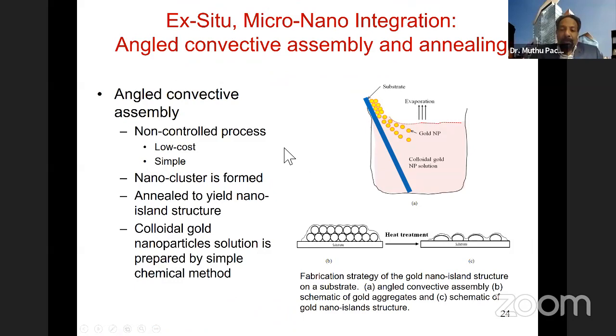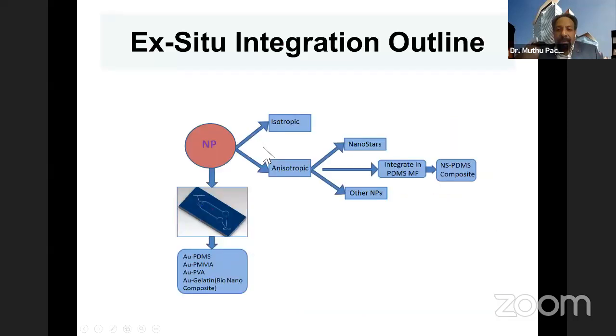In the ex situ micro nano integration aspect, as we see here, we use an angled convective assembly approach, where we produce nanoparticles and we keep the nanoparticles in colloidal solutions, and we immobilize them on the substrate by angled convective assembly, where a self-assembled monolayer or a few layers of nanoparticles can be immobilized onto the substrate, and then that's used for further diagnosis.